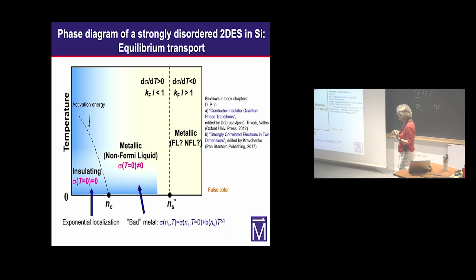And by tracking how this zero temperature conductivity changes with density, we are able to see that this goes to zero at exactly the same value of the critical density. So we get agreement from both sides of this density, which strongly suggests that this is a metal to insulator transition, and we are able to do scaling and so on. Now, importantly, all this takes place in the regime where k_F l is less than 1, where the mean free path is smaller than the wavelength.